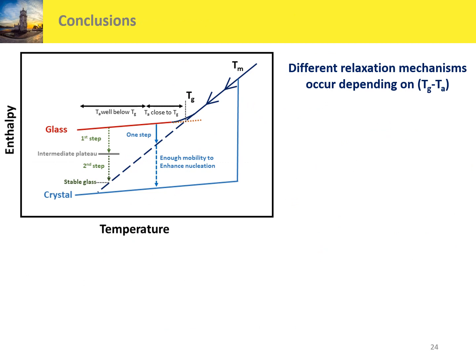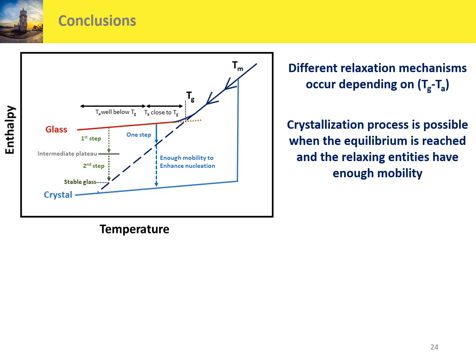So now, to conclude, we can say that thanks to calorimetric investigations, performed by classical DSC and fast scanning calorimetry measurements, we evidence different relaxation mechanisms occurring during the physical aging process, and this mechanism depends clearly on the gap between the glass transition temperature and the aging temperature. We evidence also that the crystallization process is possible when the equilibrium is reached and if the relaxing entities have enough mobility. We also prove that the physical aging is accelerated by the fast scanning calorimetry measurements.